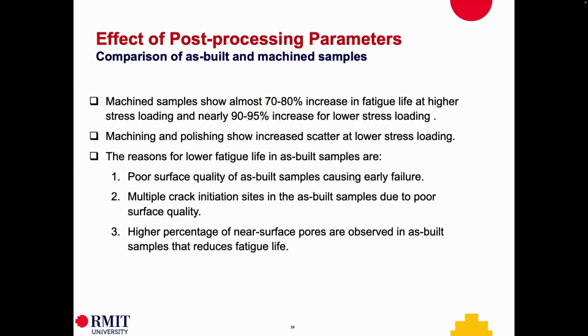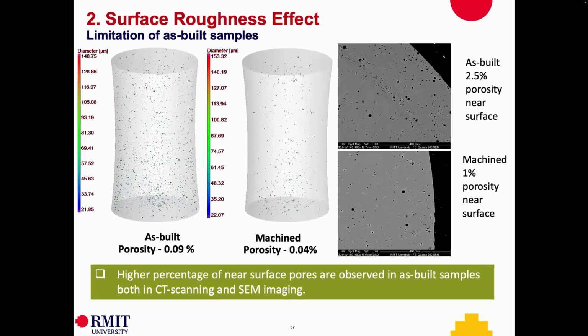Now we looked at the porosity fraction. Higher percentage of near surface pores we are observing in as-built samples. And if you have a machine surface, we can see the porosity fraction goes down. If you look at this closely at the surface, as-built sample has much larger fraction of porosities, 2.5%, as opposed to machine surface, where the porosity is only 1%. So this shows by reducing the porosity, you are actually improving the surface quality and the fatigue performance of this AM component, which is a critical factor in our AM-based material design.